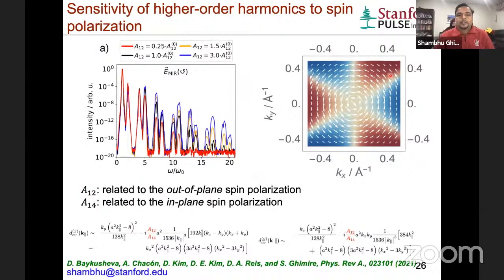Since this is a model, we can tweak these parameters and see what happens to our harmonic spectrum. We find that when you increase the ratio between these two parameters, in a way that the ratio is higher when the out of plane polarization is higher, we see a very strong enhancement in the harmonic signal. This tells us that the origin of the enhancement for circular polarization comes particularly from the out of plane spin polarization.